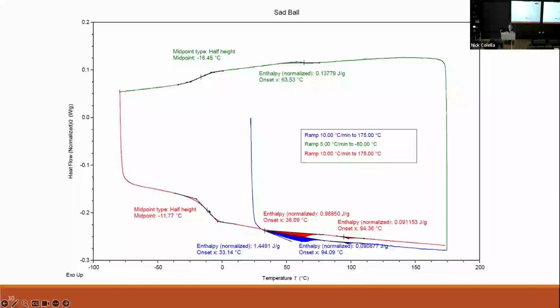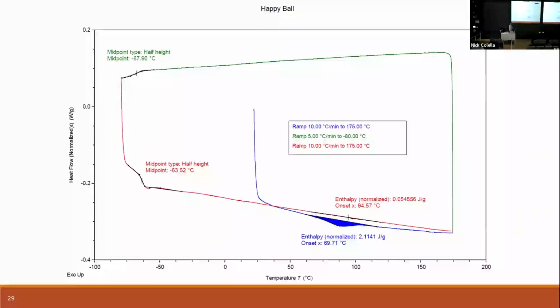And then we see our Tg starts to be around 11 or negative 12 degrees. And then we again see the melting. So this one actually does recrystallize and we get some new melting upon the second heating cycle. So very different from what we saw for the happy ball. So again, more hints that we are working with different materials.